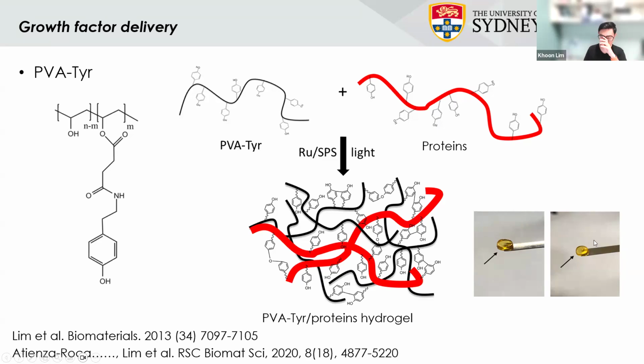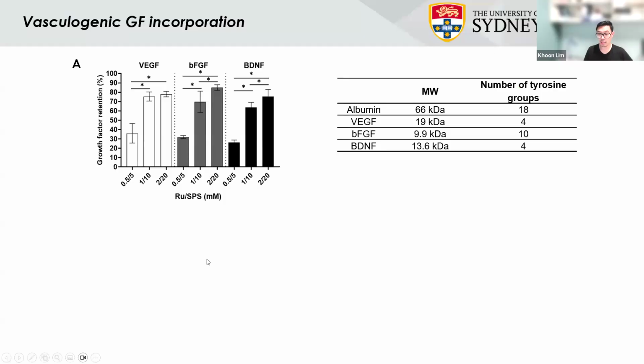So this is just a gel that I show, and we're using this for controlled release of therapeutics in this case. So we proved that you can start putting growth factors in them. We have an interest in vascularization. So we look at vasculogenic growth factors, so vascular endothelial growth factor, basic fibroblast growth factor, brain-derived neurotrophic factor, for example. You can incorporate them. Depending on the concentration of photoinitiators that you use, you can control how much you keep within these hydrogels. So we've looked at that.